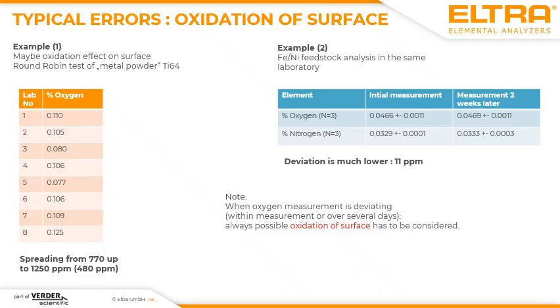For example, we also made some other examinations with iron-nickel feedstock samples here. We got this sample in, let's say, an argon-flushed glass, analyzed it immediately, and after 2 weeks again. And here we are not facing a problem with surface oxidation, just due to the fact that maybe we have a constant oxidation of the sample, which means when once oxidized, maybe no further oxidizing takes place. This is something which cannot be predicted for every metal powder, but please be aware that these effects could take place and that you can get irritating results, although everybody has measured the samples correctly.